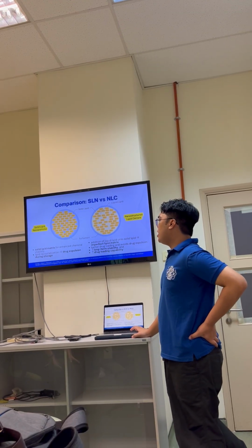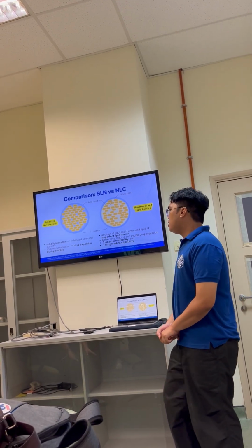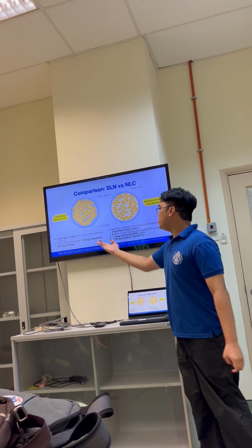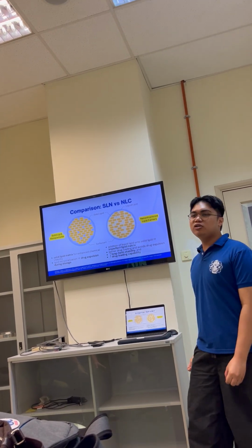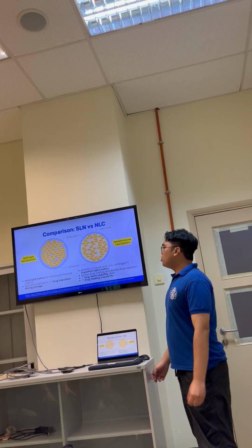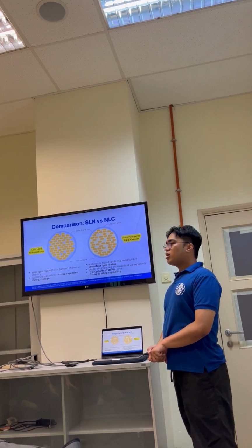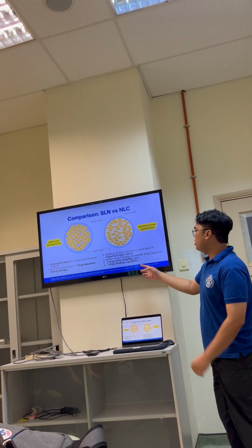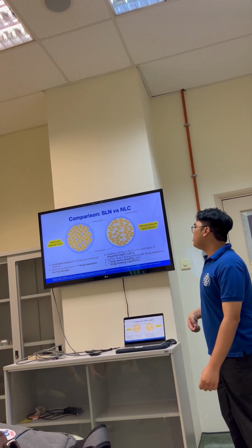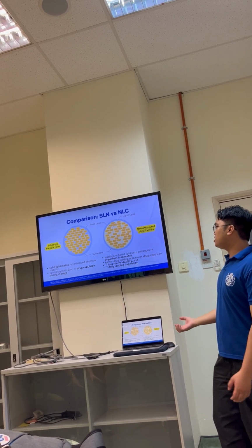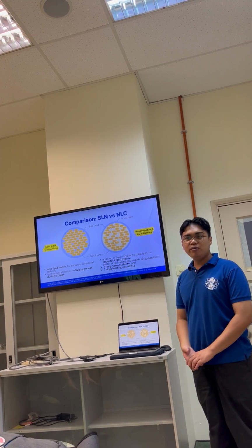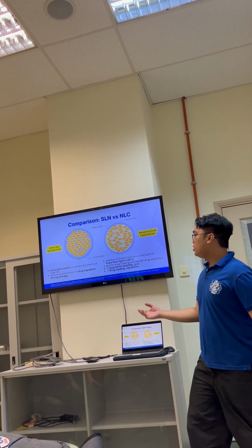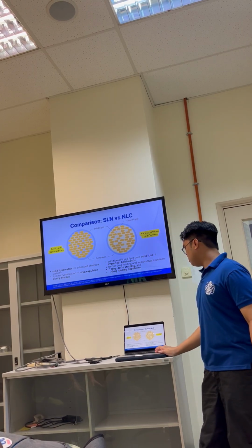matrix for enhanced chemical stability. However, this has a drawback, and the disadvantage would be that lipid recrystallization can cause drug expulsion during storage. So how do we combat this problem? We add liquid lipid onto the solid lipid to actually create the imperfect lipid matrix. And because of the imperfect lipid matrix, we get better stability in the long term and also greater drug loading capacity. And that is the difference between SLN and NLC.